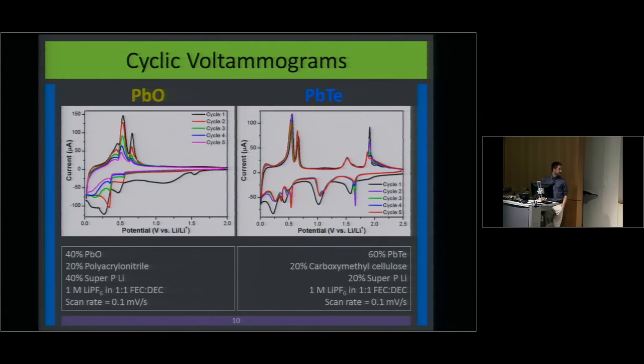We can see this graphically with these cyclic voltammograms. Basically, anything to the left of 0.7 volts is those lead reactions that I showed you, the last 4, and you can see those are pretty similar for both materials. Anything to the right of 0.7 is either tellurium versus oxygen. You can see here this hump that appears in the first cycle for lead oxide, but it doesn't appear anywhere else—that's that irreversible reaction of lithium oxide. If you kind of integrate this curve, that's a lot of capacity you're losing on your first cycle.